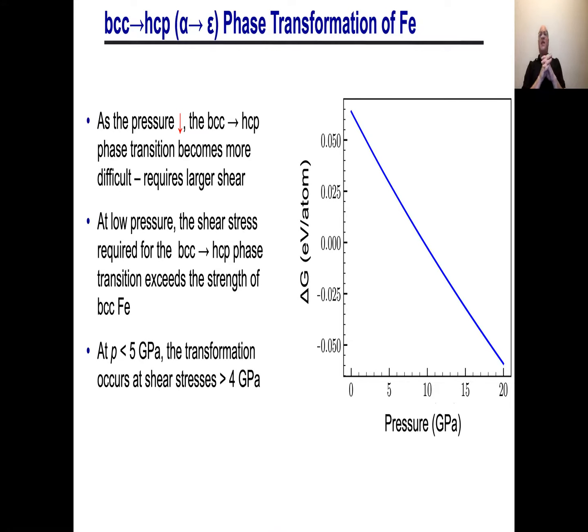if I look at the free energy difference, delta G, as a function of pressure for the BCC and HCP phases, what you can see is that as I increase the pressure, when it comes to about 9.6, then delta G is 0. So that's right there, okay? If I increase the pressure farther, then it wants to be HCP, and if I go less than that, it's positive, and it doesn't want to transform under hydrostatic pressure because delta G is greater than 0.